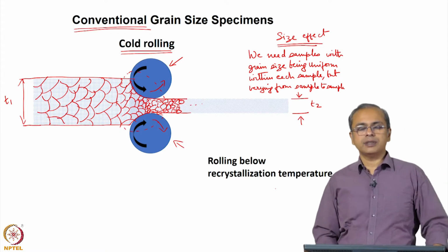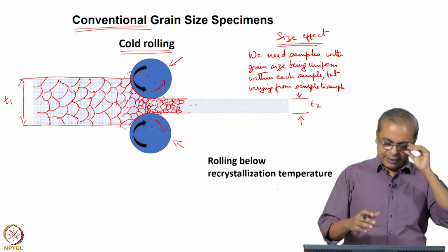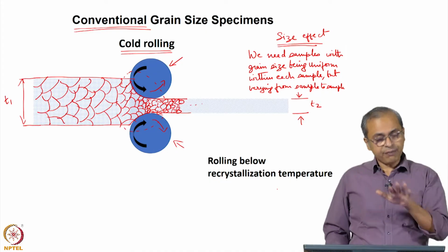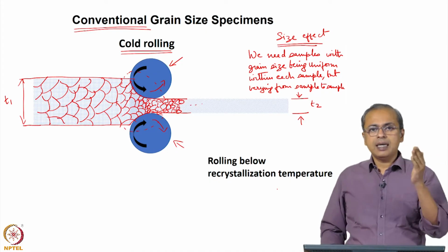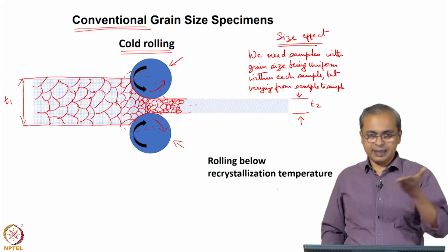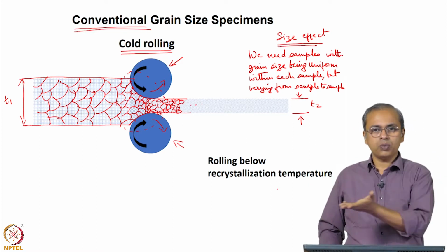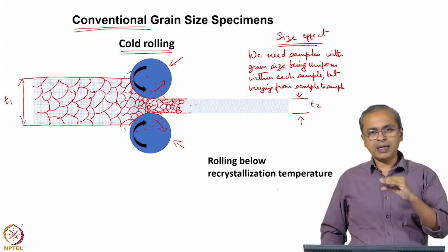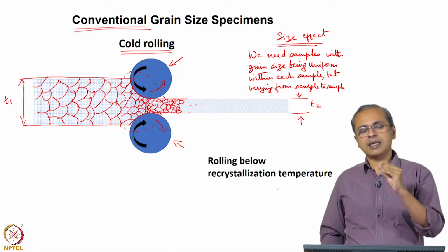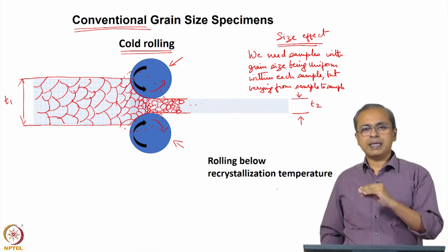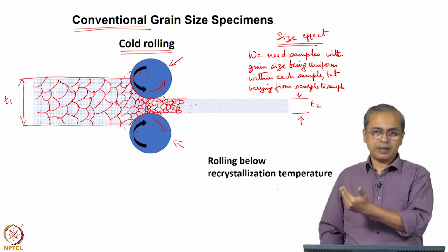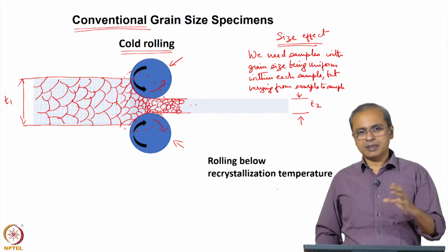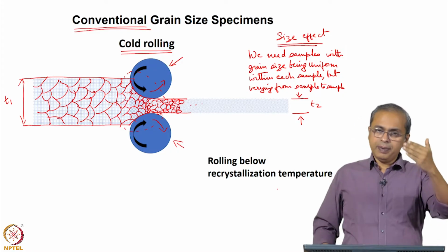So, this is a typical rolling process, and there are some restrictions. I mean, this is a schematic, so it looks like you can take a very thick material and roll it down to a very thin material. Normally, and in fact, it is true that you can eventually do this. Normally you will not do this in a single pass, each time it goes through it is a pass. So, you send it through and you get it out to the other side. You normally will not do it in a single pass, there are restrictions on what you can do in a given pass, given the stresses that are involved, given the kind of behavior of the material and so on. So, if you want a nice smooth sheet coming out, there are some restrictions on how much you can reduce. So, reduction per pass, there will be some restrictions. Within those restrictions you can do it, but you can continue this repeatedly.